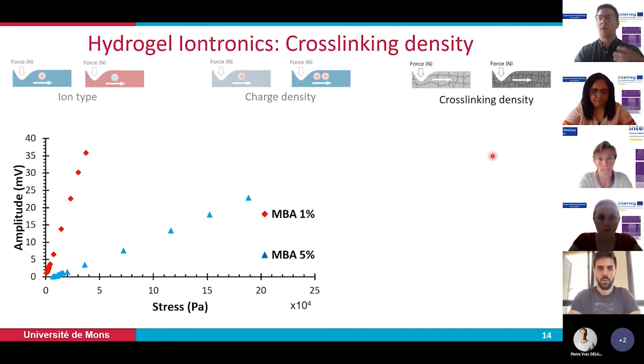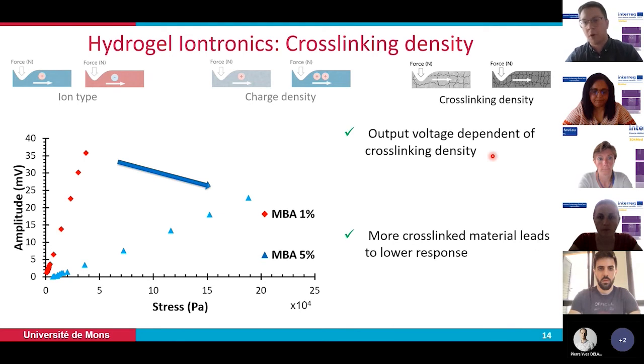And then looking at the cross-linking density, you also have a dependence of the voltage on this cross-linking density. And as expected, more cross-linked materials, so more compact materials, lead to a lower response because you lower the mobility of your ions inside the materials. So this is completely expected.